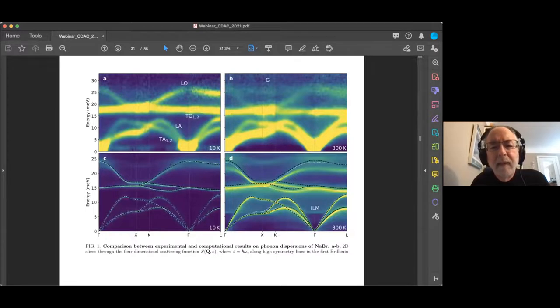This is 10 Kelvin. We have measured and calculated phonon dispersions, which are in reasonable agreement at this low temperature. At room temperature even, we see a new feature here, which grows with temperature. And our collaborator, Mike Manley, had been looking for intrinsic localized modes that we don't really see at 300 Kelvin, but we do see them at 400. They do show up in that case. So these are additional branches, which are showing up, and they're temperature dependent, and they are associated with anharmonicity in the sodium bromide.